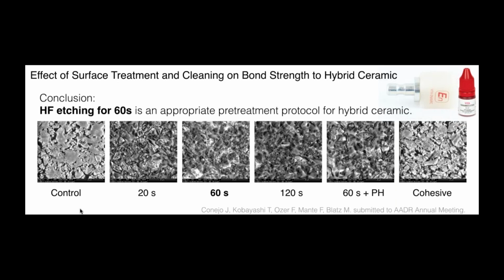So actually excessive cleaning after etching was not something that really improved significantly the bond strength. So I'm not saying etch it and work on a dirty surface. No, not at all. But just with water and air spray, removing the hydrofluoric acid etching had the same bond strength as if you did application of phosphoric acid for 60 seconds after the hydrofluoric acid etching. So some concepts that we see that apply for pressable ceramics or layered manually feldspathic ceramics do not necessarily apply for the VITA Enamic on that aspect.